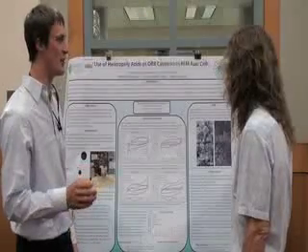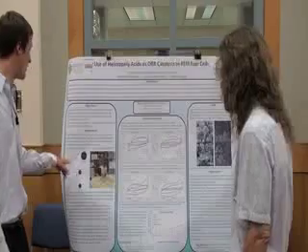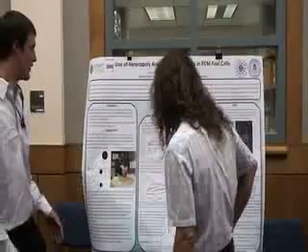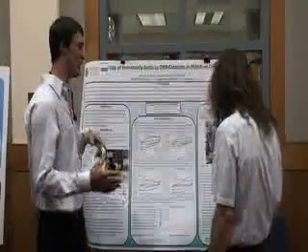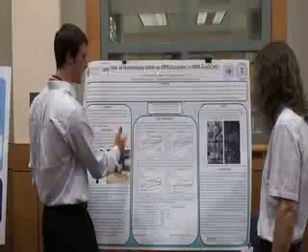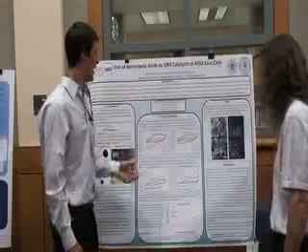And so we've created these hybrids of catalysts and carbons, where we've bonded different heteropoly acids onto carbons, so this is Ketjen carbon. We've done that covalently, and so that's kind of a unique thing that they've done. So the main test I did was cyclic voltammetry, and you start at one potential, and you go to the opposite potential, and then run back and forth. So it runs in a cycle, multiple cycles.